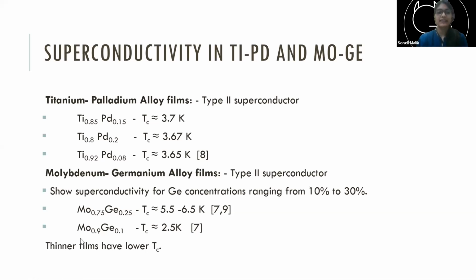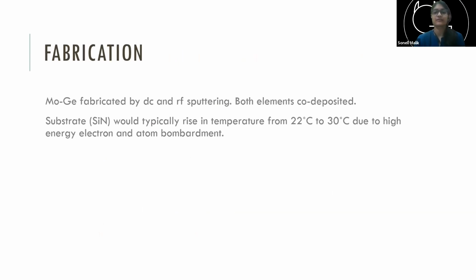Oh, so another thing. Depending on the thickness of the film, the transition temperature can change. So the transition temperature for the bulk is say 5 Kelvin, but if you have a film with thickness of say 10 nanometers or 15 nanometers, its transition temperature could be only say 3 Kelvin. So that is again another thing you need to look out for in thin films.